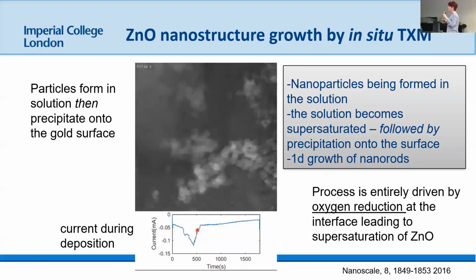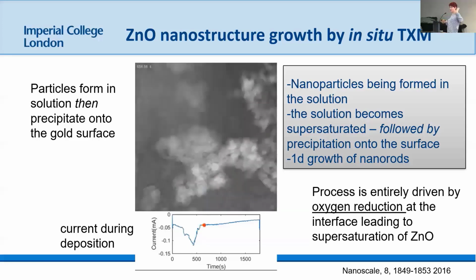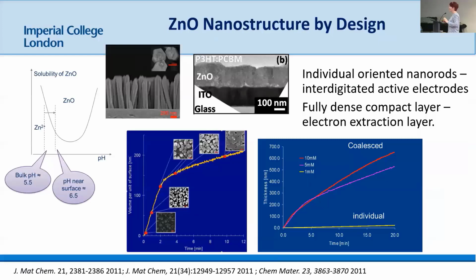So there was some question about whether there's a solution formation and then a precipitation, or whether things nucleate on the surface directly and grow out. So this shows really clearly there's a solution supersaturation. One, we can measure it, which is pretty cool. But two, it separates out those two mechanisms. The solution drives it, and then it precipitates. And then the growth is dependent on the rest of your conditions.